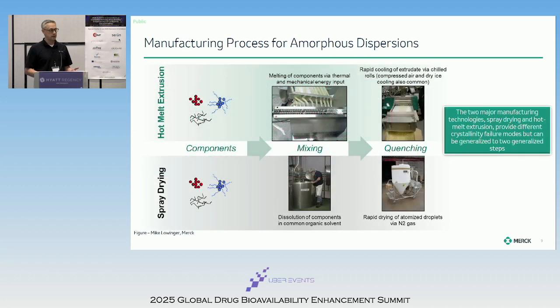So pulling it back to the two basic technologies that nearly every organization is going to use comes down to hot melt extrusion and spray drying, and some of the talks already in the last 2 days have addressed these technologies. But I like to think about both of these technologies, while very different, and we'll talk about the differences, actually come down to two basic steps. And this is an analogy that my colleague Mike Lowinger had actually developed. It's going to consist of a mixing step and a quenching step. In the case of extrusion, the mixing step is very challenging. You're going to be mixing your materials at elevated temperature to create a single phase solid dispersion before you then go through a quenching step.